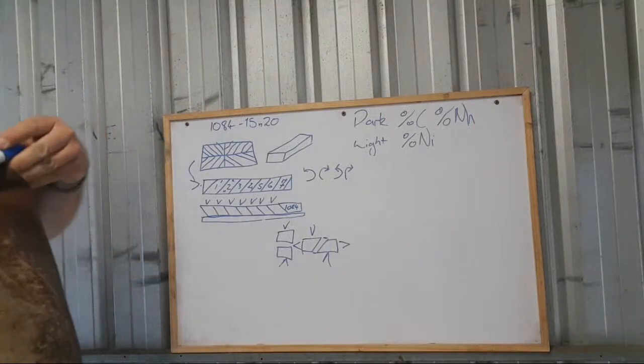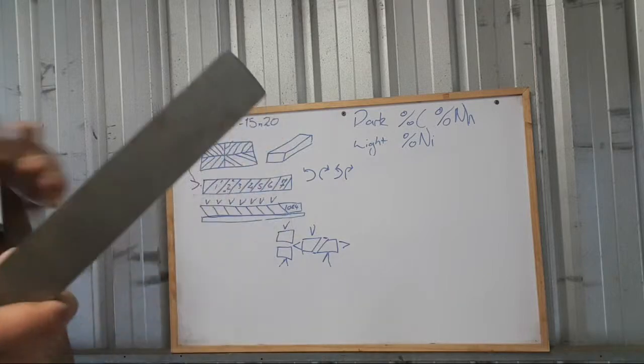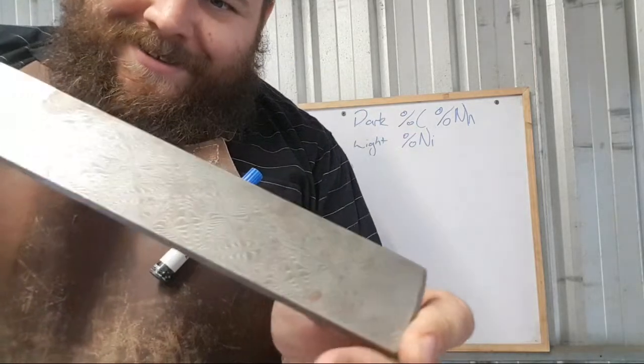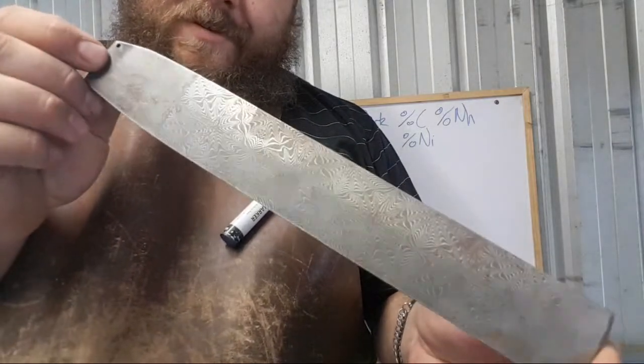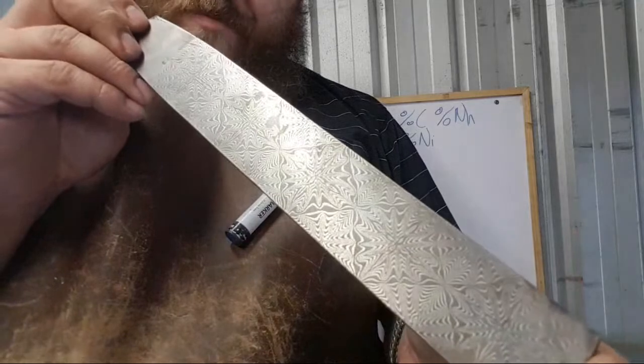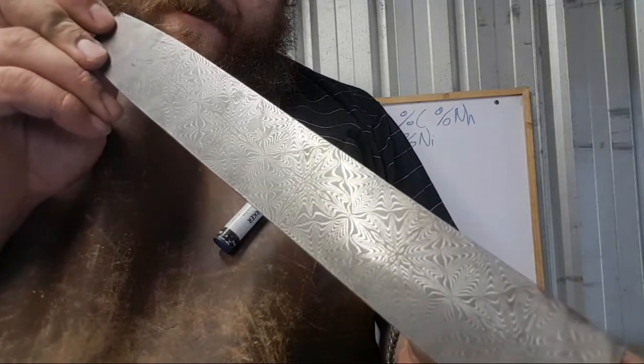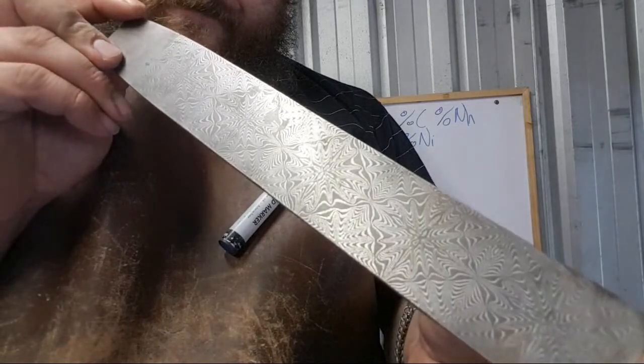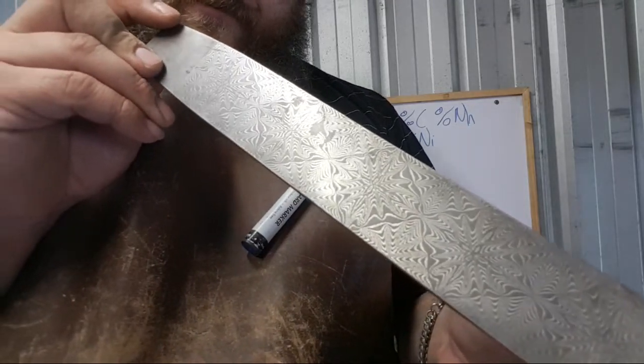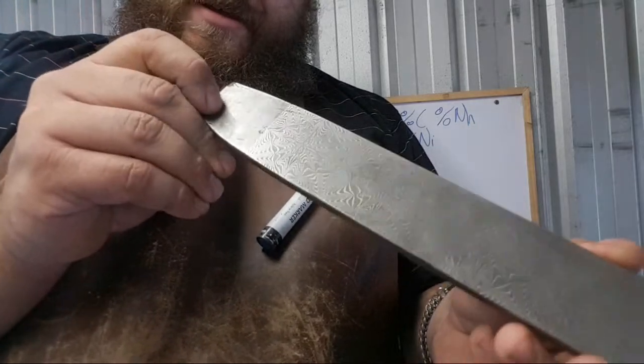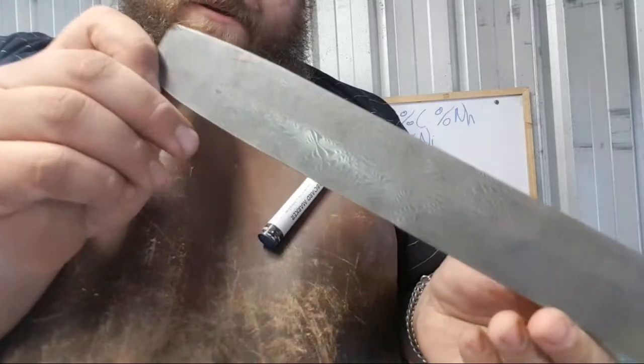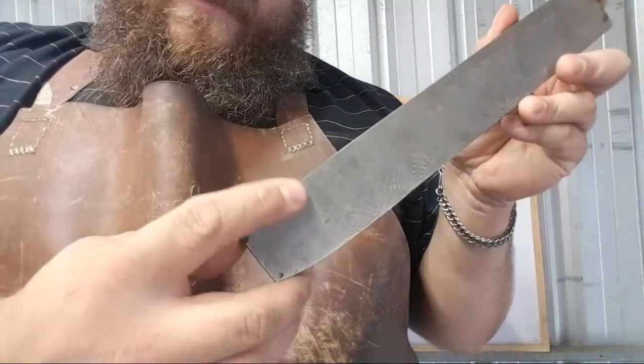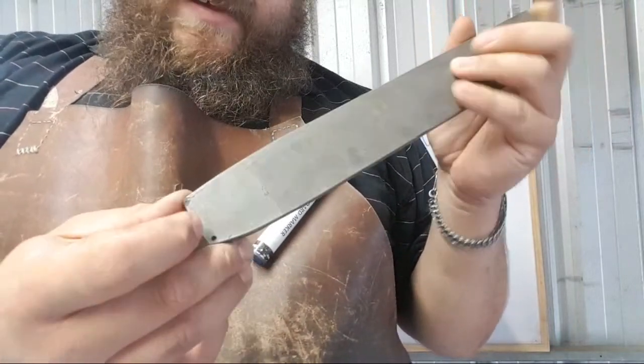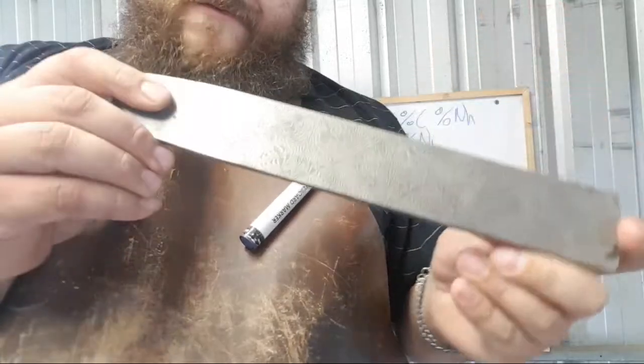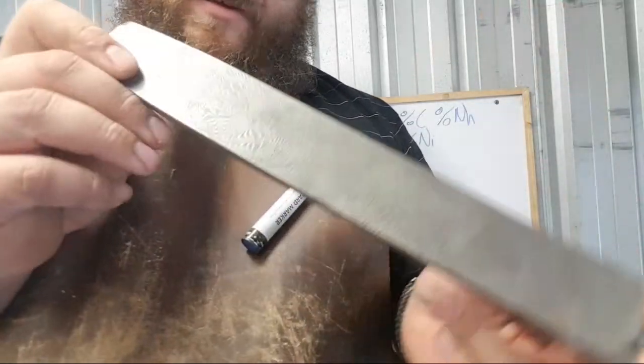So once you've completed that tiling process, and once you've completed all the welding, what you will have is this. So this is explosion pattern Damascus. Hopefully it's clear how those W's make the pattern. And you can see that this has actually been welded onto a piece of 5160 as the tang material rather than a piece of 1084. But 1084 would have been better because 5160 really doesn't like to weld.